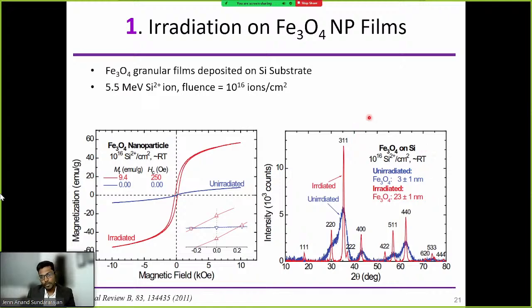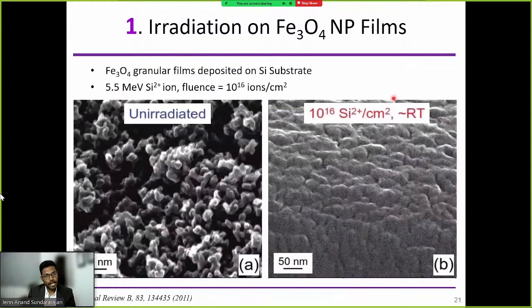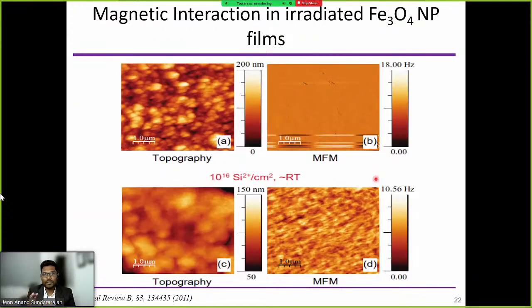Let's take a look at the surface morphology. This is how the unirradiated film looks. But after irradiation, you can see everything is conglomerated together. They kind of agglomerated together, and there is a huge change that has happened. Taking a close look at the magnetic interaction using AFM studies, this is how the particles look before irradiation, and there is no magnetic interaction here from the MFM. But after radiation, you can see the particle size has grown huge, and also you can start to see magnetic interactions happening between the sites. So irradiation did something to that, and what did it do? That's what we want to find out, right?